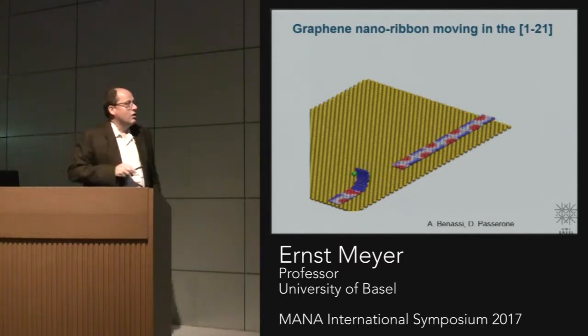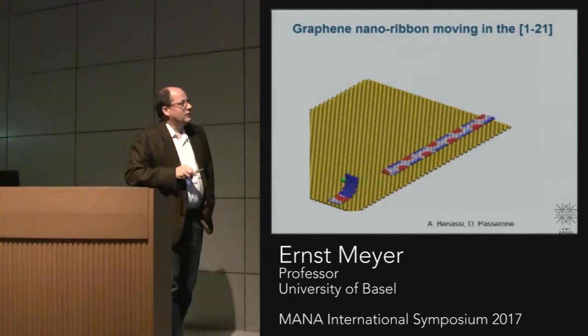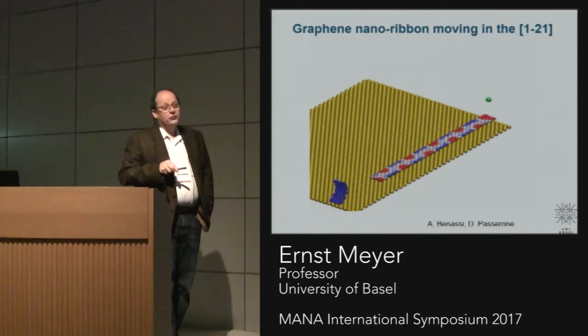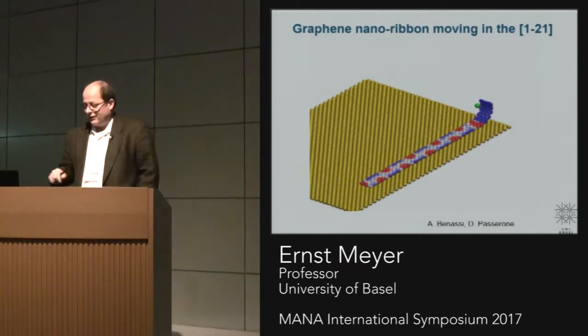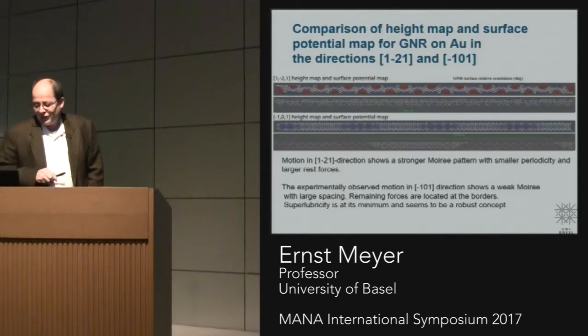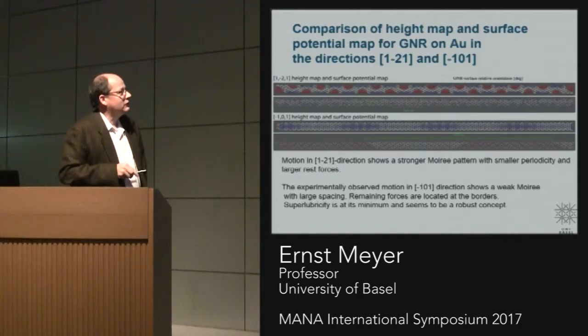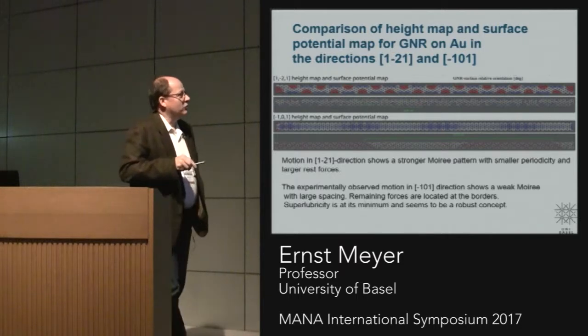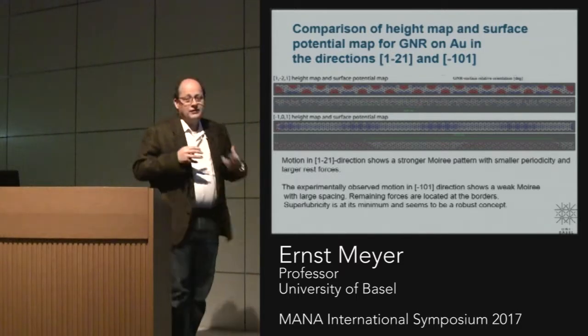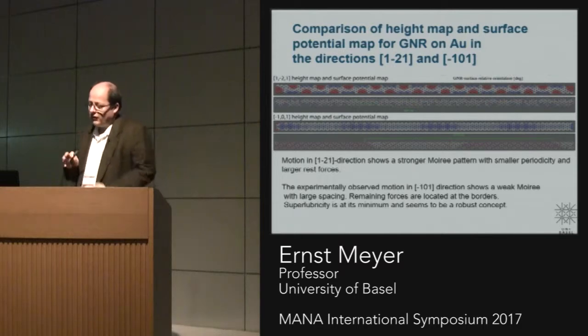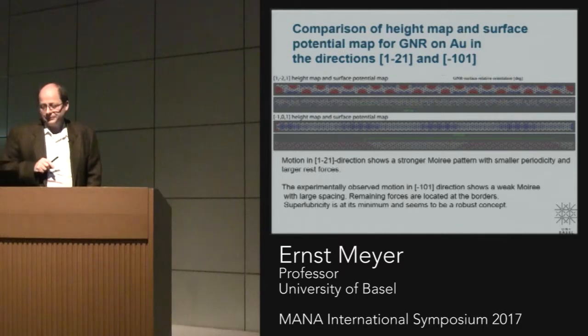It gives a bit more lateral forces, and actually experimentally we don't observe that motion. So actually nature prefers the first case. So this is shown here again. The upper one is in the [1-21] direction. So this one gives a little bit larger force, and in the experiment we have this case where it's basically nearly no, or a very weak, Moiré pattern.